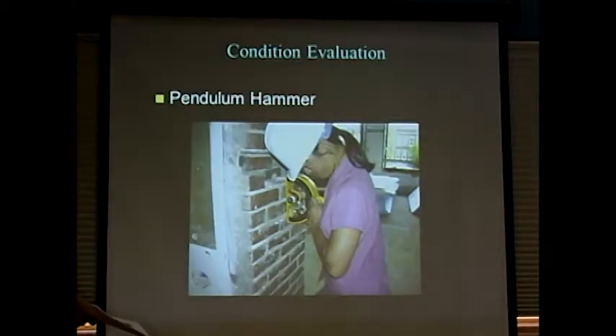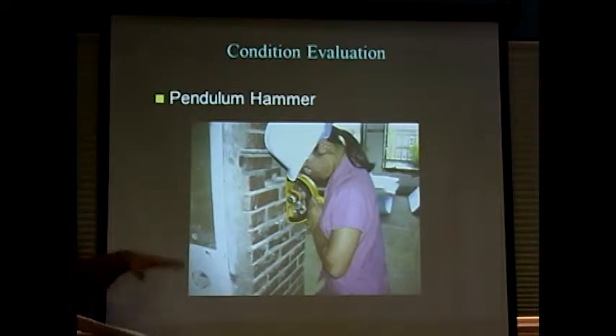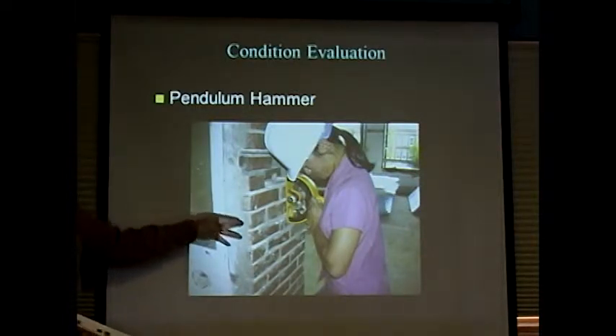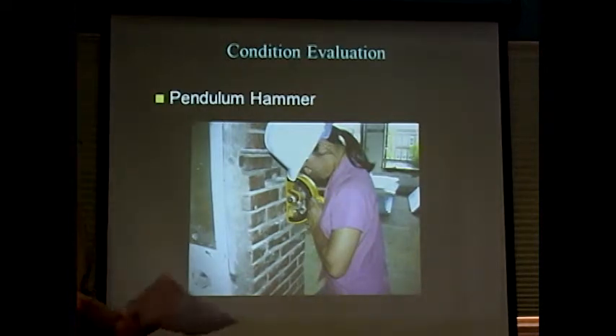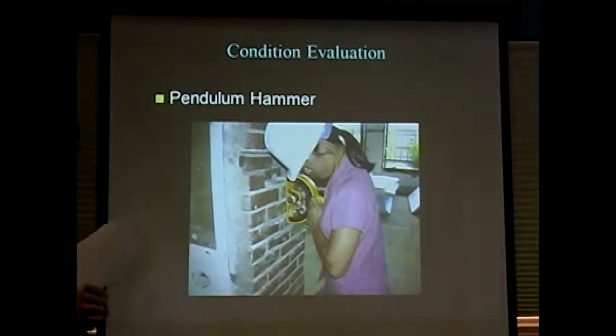So because of this observation, we came up with some solutions. We'll see that in a moment. Now, we ran some pendulum hammer rebound hardness tests to look at the mortar hardness throughout the exterior and interior. The building had been repointed 15 years prior, and like a lot of repointing projects, there was concern that maybe they used too hard a mortar, a high cement mortar. So luckily, with the results of this hardness test, testing the hardness of mortar at different areas around the building, we found that the repointing mortar was only maybe 25% harder than the original mortar.